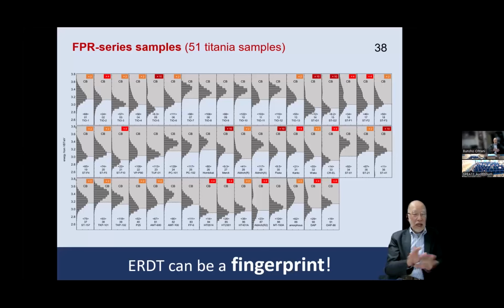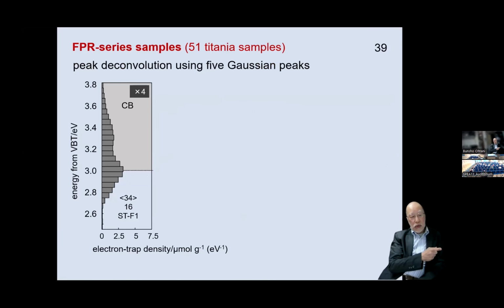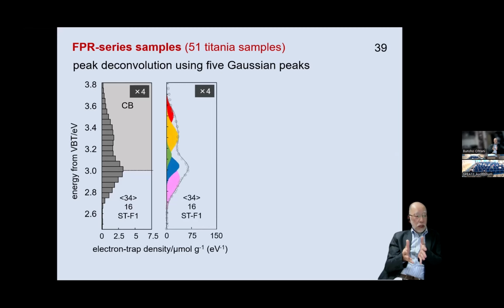There is no actual information of surface structure. So then we noticed this pattern. This has very wide range peaks. And actually, it seems that this pattern is a summation of different peaks. And we assumed 5 Gaussian peaks for fitting the data. And this is deconvoluted into 5 peaks.